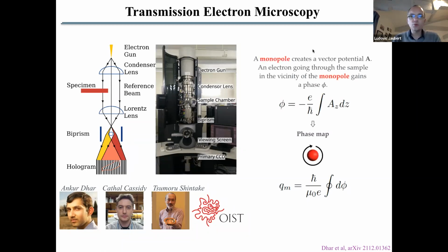So, the point is, what happens if you have a monopole? What happens if here in this sample you have a magnetic charge? Well, if you have a magnetic monopole, we have a vector potential A, and Az is parallel to the electron beam, so it's orthogonal to the sample. And an electron going through the sample in the vicinity of the monopole will gain a phase phi through the Aharonov-Bohm effect, simply by being in the vicinity of